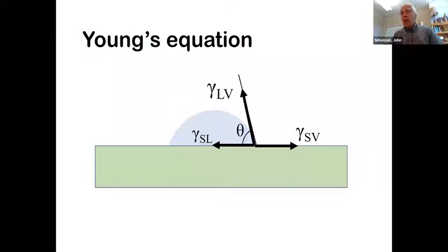So another way to look at whether the wood has a high or low contact angle is to just take a drop of water, put it on the wood, and time how long it takes to be absorbed. If it's absorbed slowly, you have a more hydrophobic surface. If it absorbs quickly, you have a more hydrophilic surface. And that'll give you a clue as to what's going to happen with the adhesive too.